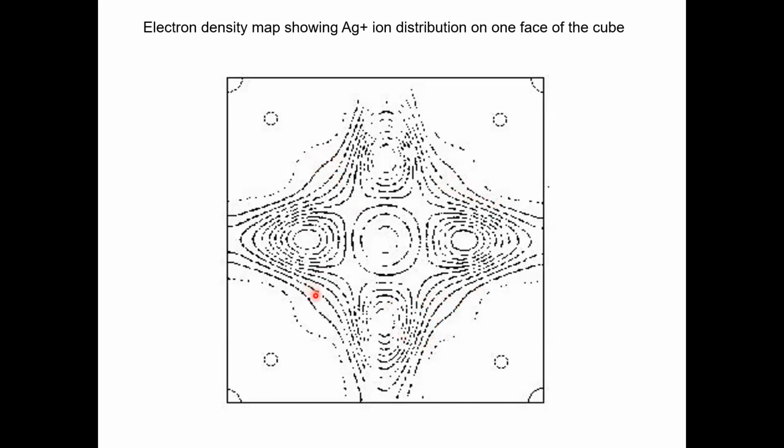But remarkably, this electron density map shows that they are diffused. So the silver is not sitting necessarily around the tetrahedrally coordinated sites. So they're all over the place. So this shows this diffusedness in the silver mapping. Silver density mapping shows that silver is almost everywhere.